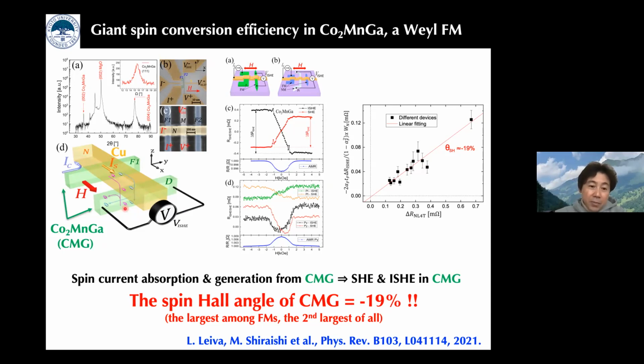Thanks to the topological effect in CMG, the absorbed spin current is efficiently converted to charge current, yielding the electromotive force. And we observed the spin Hall and inverse spin Hall signals, and we clarified the breaking of the orthogonal reciprocity in this material. And also we quantitatively estimated the spin Hall angle of CMG to be minus 19%, a very large value.